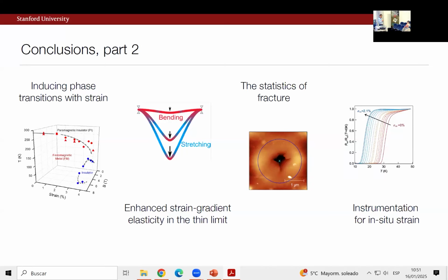It turns out that, at least if we take the numbers we deduced from these mechanical measurements, let's say 5 nanometers of a manganite sitting on, I don't know, 12 microns of Kapton or something like that, they're kind of mechanically equivalent. And you're kind of envisioning this is a very, very minor feature in this case. But I will give you another example.